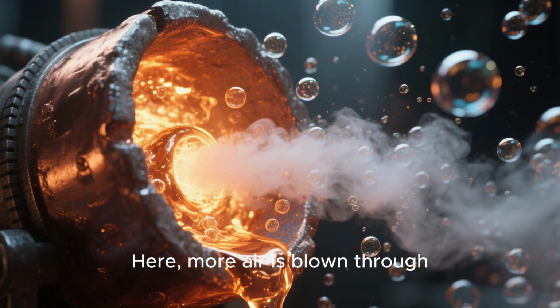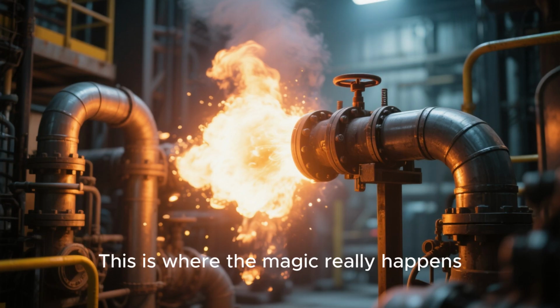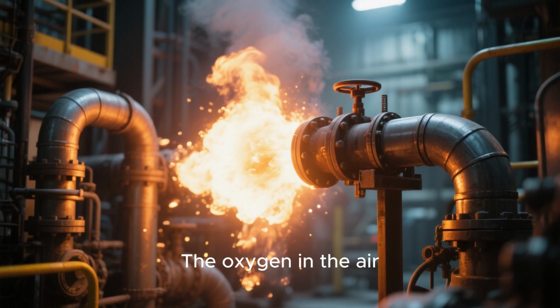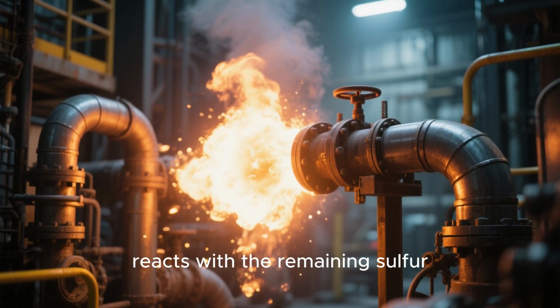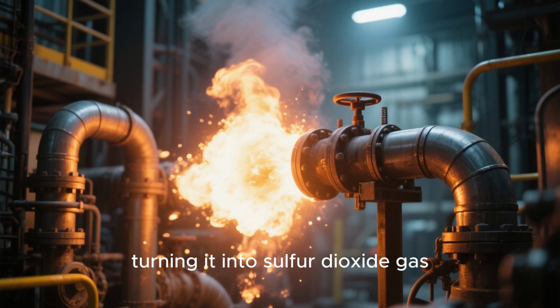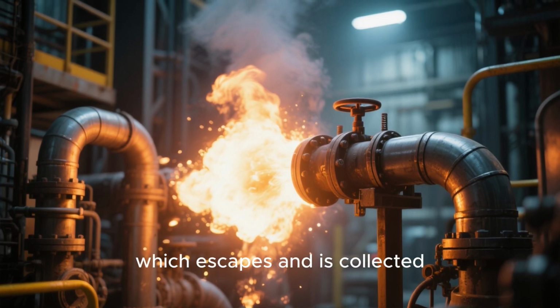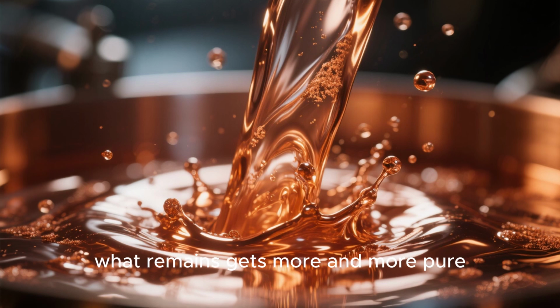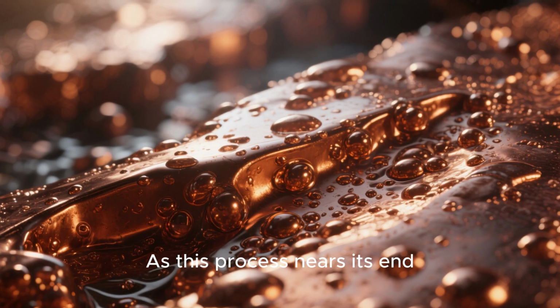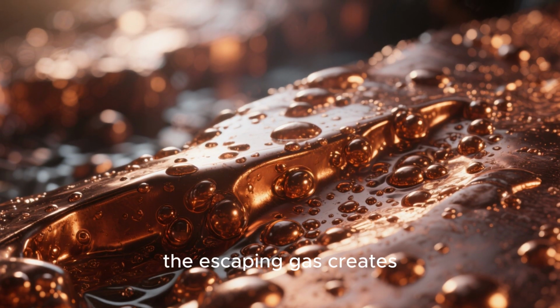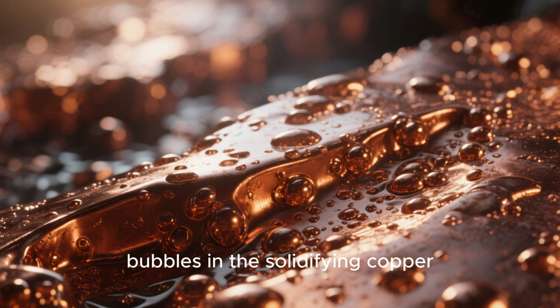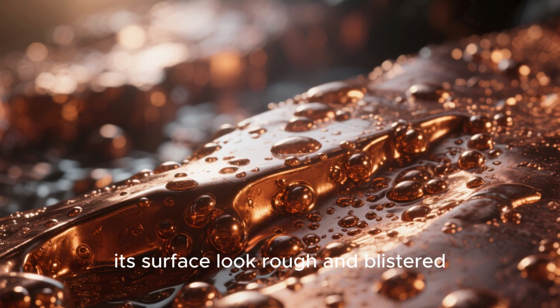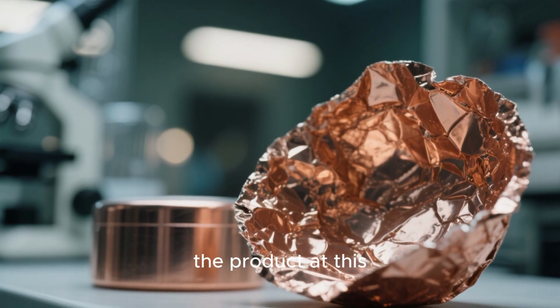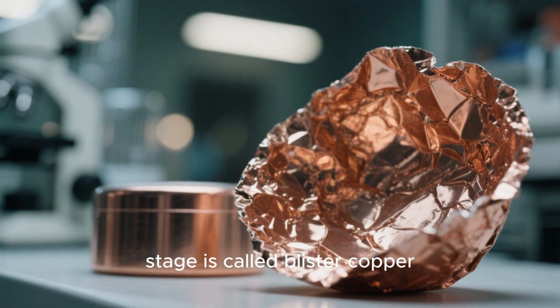Here, more air is blown through the molten liquid. This is where the magic really happens. The oxygen in the air reacts with the remaining sulfur, turning it into sulfur dioxide gas, which escapes and is collected. As the sulfur leaves, what remains gets more and more pure. As this process nears its end, the escaping gas creates bubbles in the solidifying copper, making its surface look rough and blistered. Because of this appearance, the product at this stage is called blister copper. We've made a huge leap. Blister copper is about 99% pure copper.